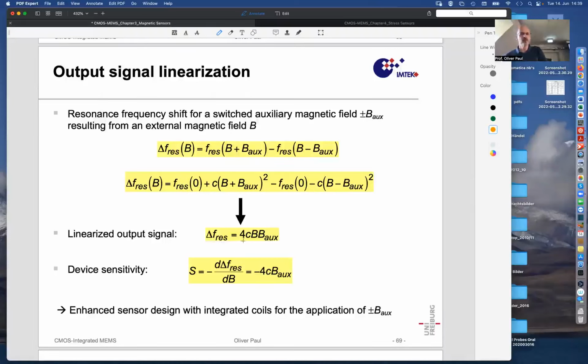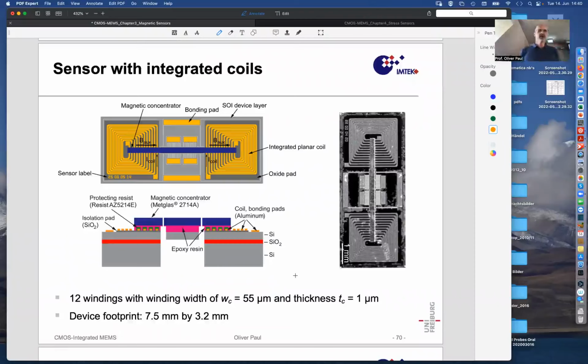So how to produce a sensor with integrated coil to have an auxiliary field generated in situ of the sensor. That's the next challenge of Simon, and he did this by taking his original structure and adding some planar coils on the surface of the chip, as you see here, with 2 pads that can be bonded, to which a current can be sent through to generate a magnetic field. Same on the other side, where the auxiliary magnetic field will point now downward, the one on the left outward, and then this field is sucked into the concentrator and out of the concentrator into the other coil. So this is the way to make an integrated Helmholtz coil, a flat 2D Helmholtz coil, which does no longer serve the purpose of making some field homogeneous, but it generates an auxiliary field, and that's all we want.